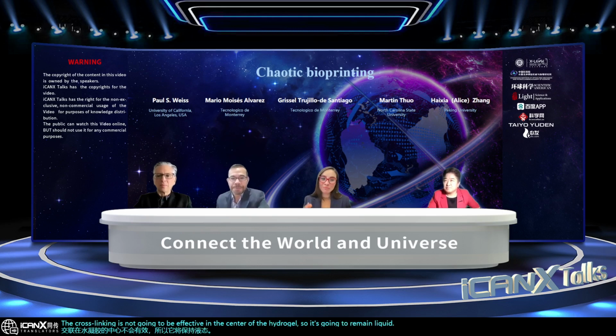If you want that, that's perfect. In that case, you will have a hydrogel with a big hollow channel inside, right? But yes, you can control that, and it's going to depend on the material, the cross-linking method, and of course, we want to preserve the viability of cells. So our advice will be to use wide nozzles so we don't have very high shear stress that can affect the cells. Okay, this was super.